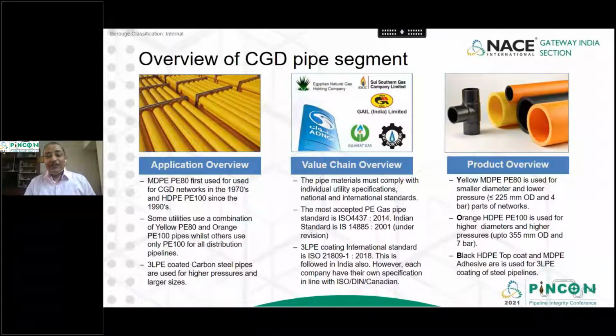An overview of city gas distribution pipe segments. MDPE PE80 pipes were first used by British Gas in their CGD network around 1963, and HDPE PE100 started being used in the 1990s. Some utilities use a combination of yellow PE80 and orange PE100, while others use only PE100 for all their distribution pipelines. Three-layer polyethylene coated carbon steel pipes are used for higher pressures and larger sizes.